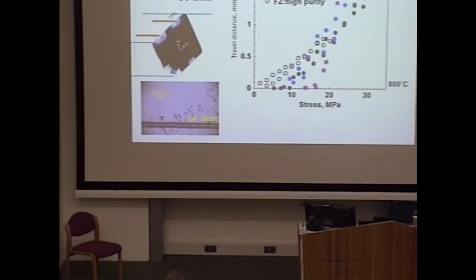So for experiment, how do we determine this kind of activity of dislocations? This is a sketch to measure the dislocation activities. For example, at first, take silicon, and introduce a scratch on the surface as a dislocation source. From the dislocation source, dislocations appear like this. From the scratch, 60 degree dislocations appear. And in high-purity crystals, dislocations are easily generated from low stress. This open circle shows the high-purity silicon.